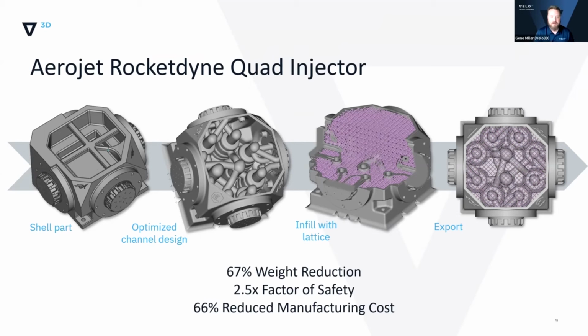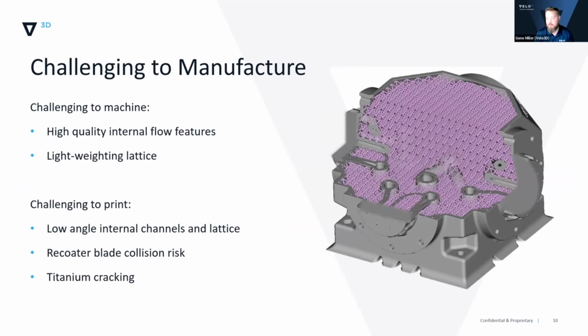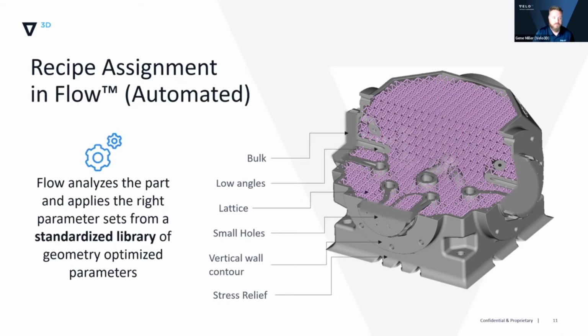The original part consisted of many different parts, a lot of assembly steps, and a lot of other sources of failure, to be honest. So this would be practically impossible to machine. If you could machine this, I have no idea how you could do it. Really, this lightweighting lattice makes the machining process impossible. The print itself, if you were to do this on another system, you'd still have challenges with the internal channels. The lattice structure itself would suffer from recoater contact, which Velo3D doesn't have to worry about. Also, there's the high susceptibility of titanium to cracking. We have an in situ stress reduction technique that ameliorates the risk of cracking in titanium parts.